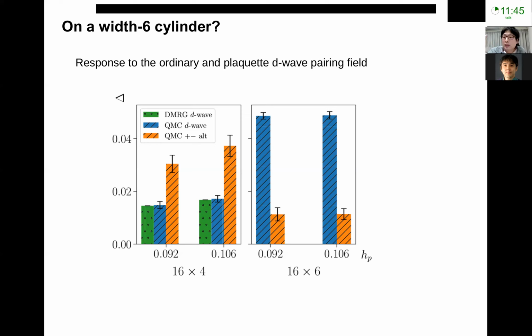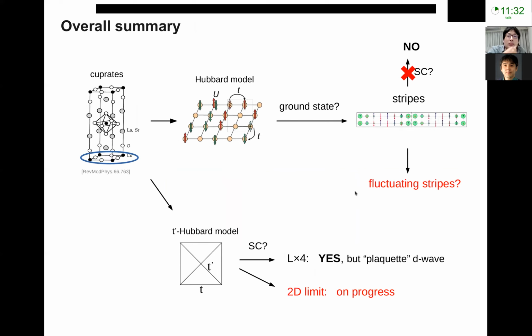So we need to pay additional attention - we need to be especially careful about this spatial geometry. This gives us a midway summary of the Hubbard model simulation: we first find that the ground state of the Hubbard model is stripe, but it's not superconducting. Whether we can start from here to get some superconducting state, for example by fluctuating stripe, is still an open question.